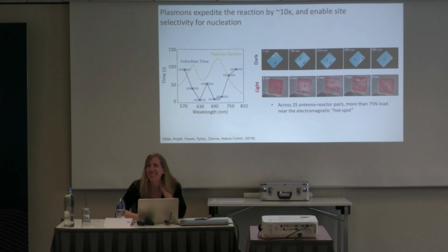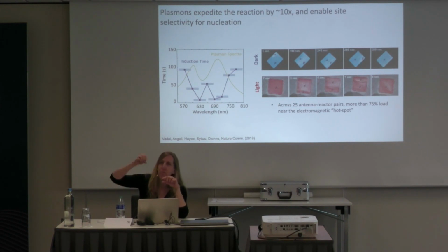Yeah, go for it. So this near field enhancement, does it match with hydrogen's HOMO-LUMO? It does? Yep. Or it matches with the HOMO-LUMO of, it's not just hydrogen, basically it's hydrogen bound or adsorbed to palladium. So people kind of call this a hybrid orbital between your palladium D and S electrons and your S electron of your hydrogen. So basically it matches with the HOMO-LUMO of that hybrid palladium-hydrogen orbital. And that is normally much lower compared to free hydrogen, right? That's right. Yeah.